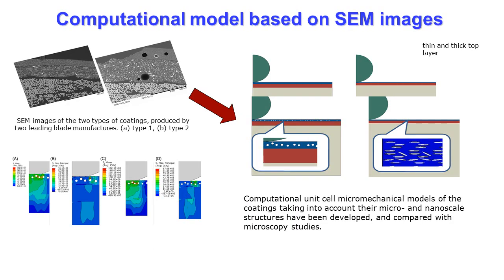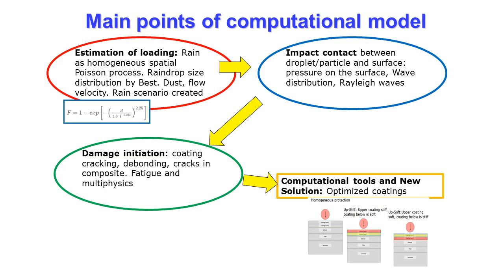Here, you see the micrographs and computational models of the coated composite samples, subject to rain droplet impact. It can be seen that the areas of high stress concentration, near voids, are exactly the areas where the damage was observed. A computational model of rain erosion usually includes several steps: rain scenario, defining the time and spatial distribution of droplet impacts, fluid impact model, and the stress wave propagation analysis, damage initiation and fatigue analysis.